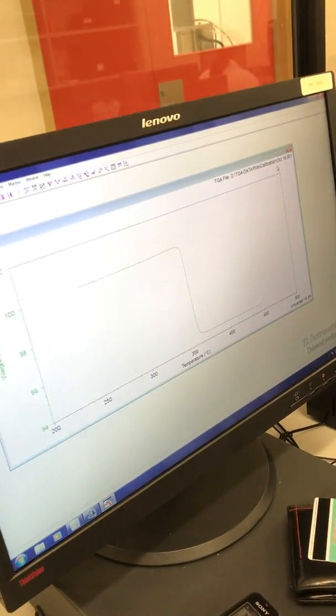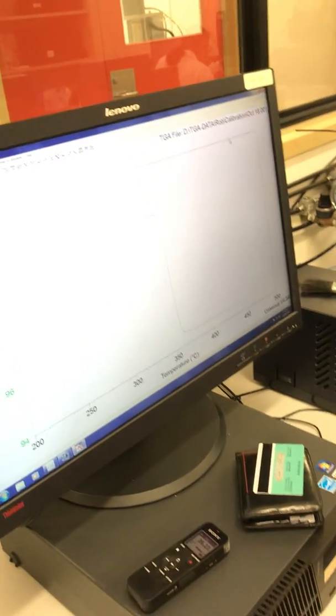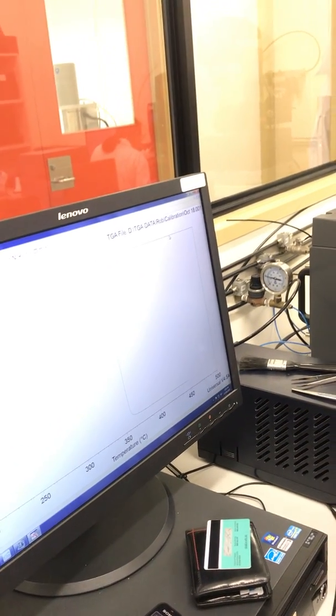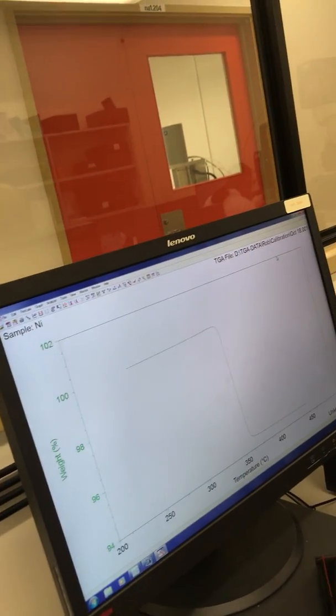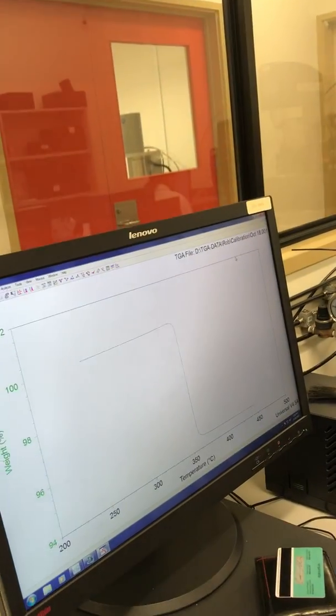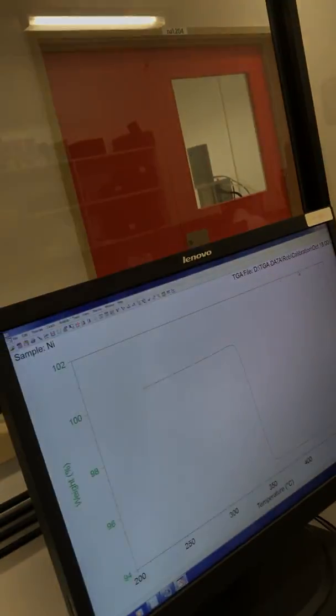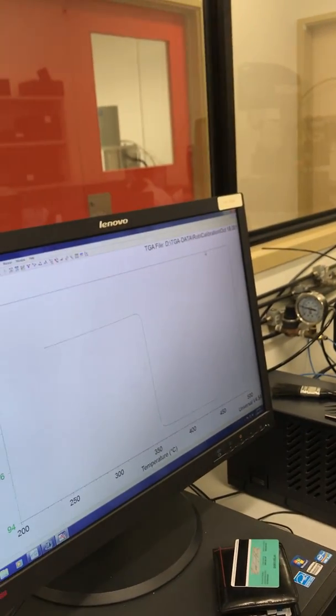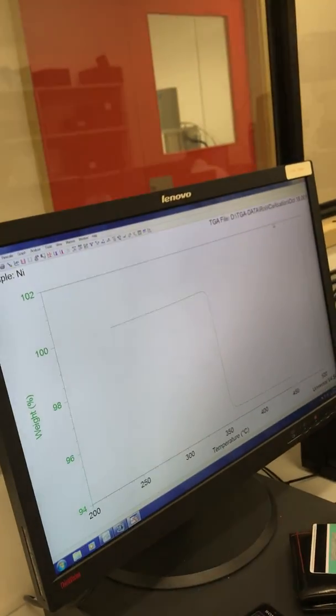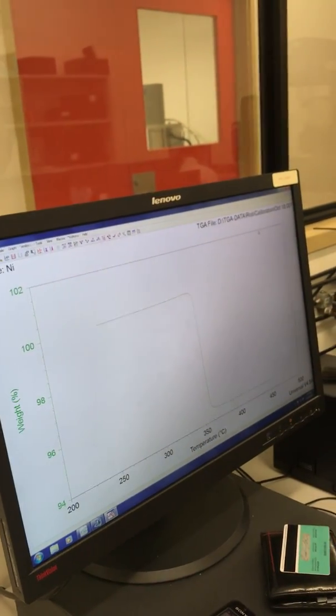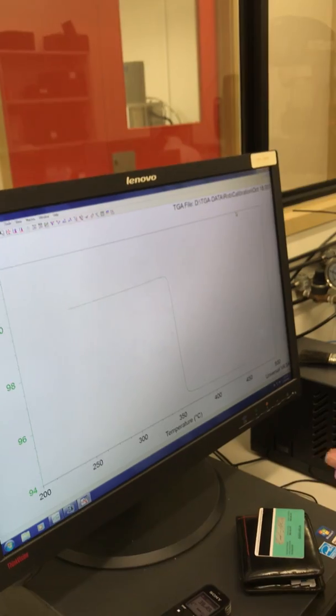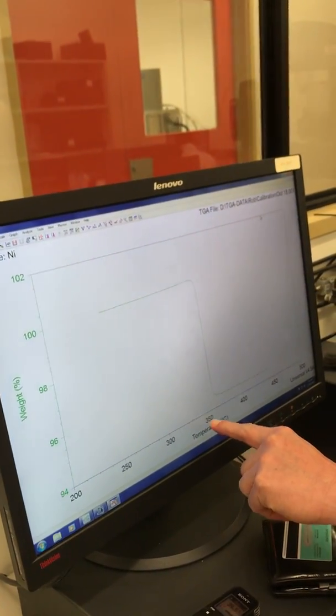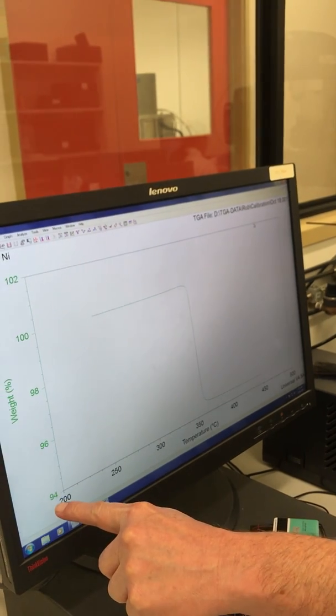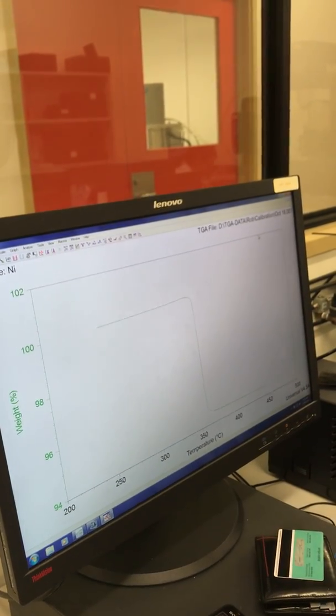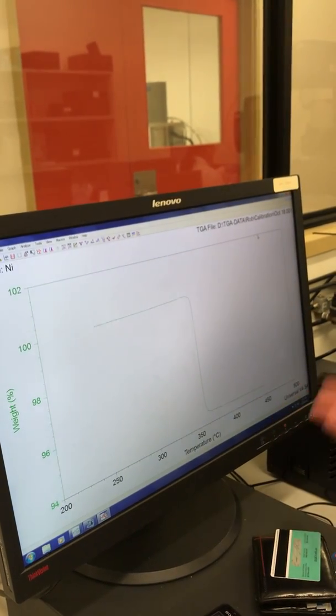This is the nickel file. I use the YouTube channel for TA Instruments, and they told me exactly what to do. I have a few settings in here. I have to make sure that when this finishes testing, the furnace doesn't come down because I've got the big magnet underneath there. So a few settings I need to adjust. I start this at 250 degrees because there's nickel, nothing happens to it before 350. This has an apparent 6% weight loss, but it's not. It's when it goes from magnetic to non-magnetic, it lifts up.